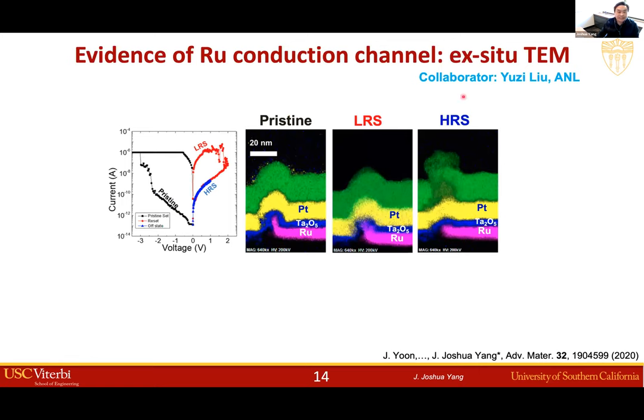In fact, we did this study with Yu Zi some time ago. And at Argonne National Lab, the TEM was done first, the ex situ TEM. In this experiment, we take three devices, we put them into different states: pristine state, low resistance state, high resistance state, and then we cross-section them and look at TEM. As you can see here, for the device in pristine state, the ruthenium and platinum electrodes are well separated by the oxide layer.